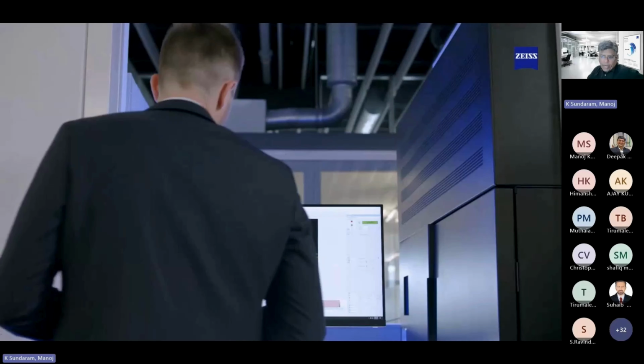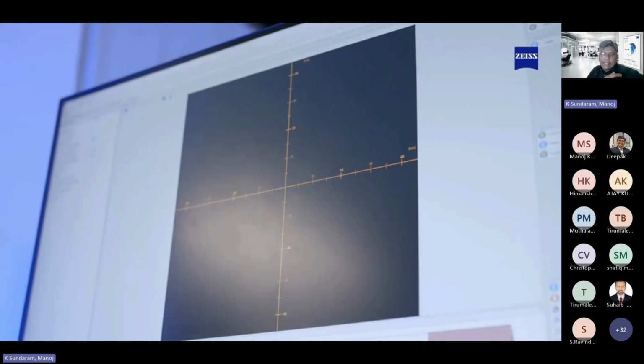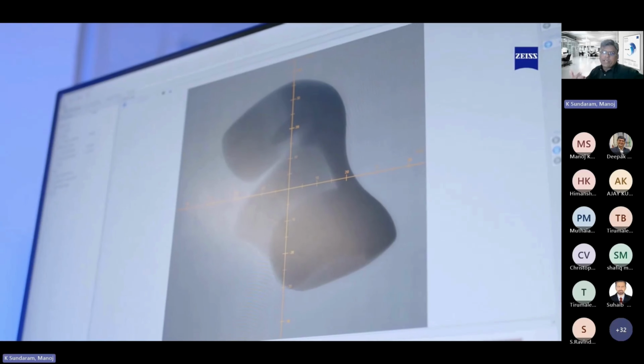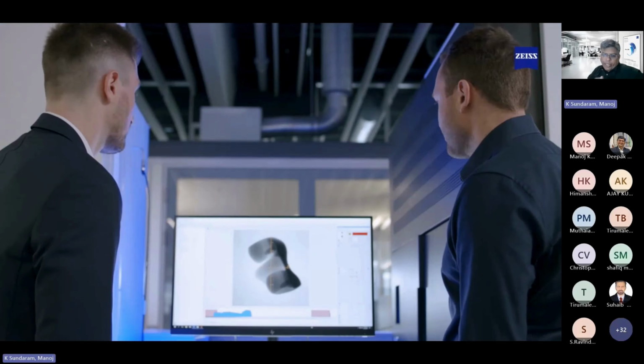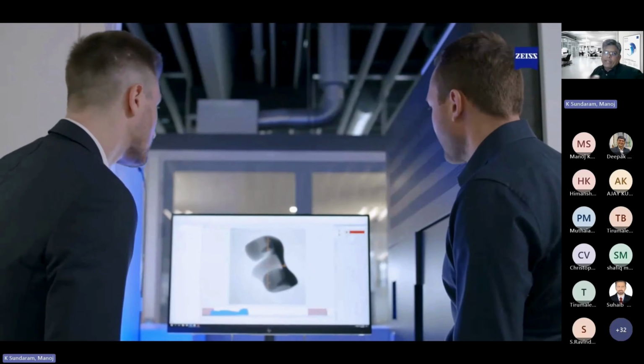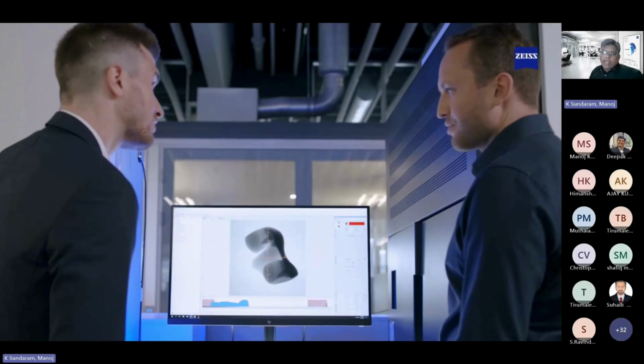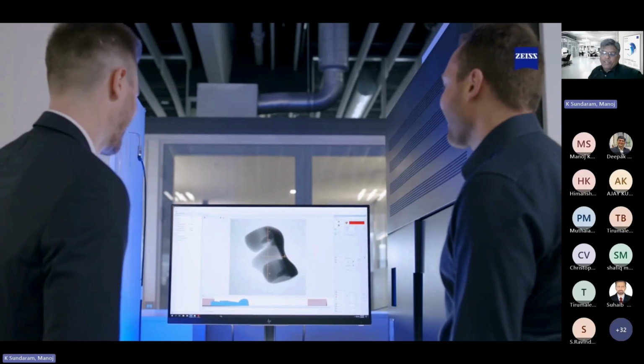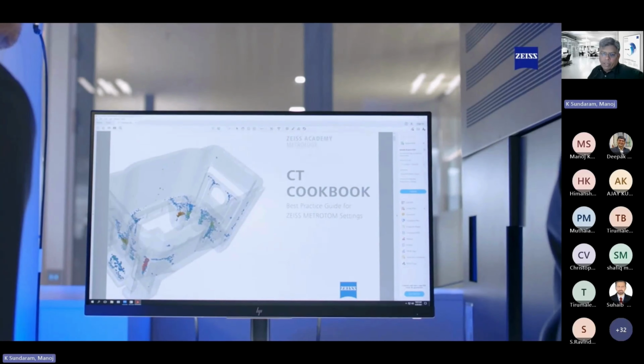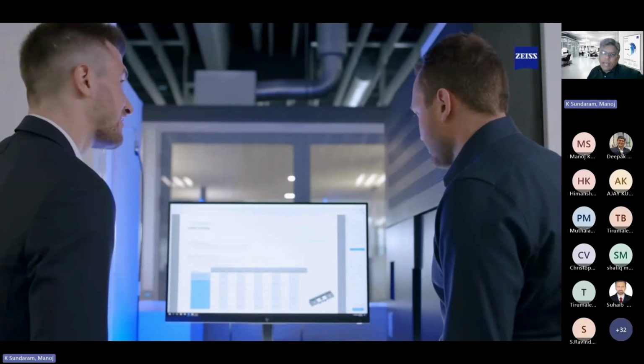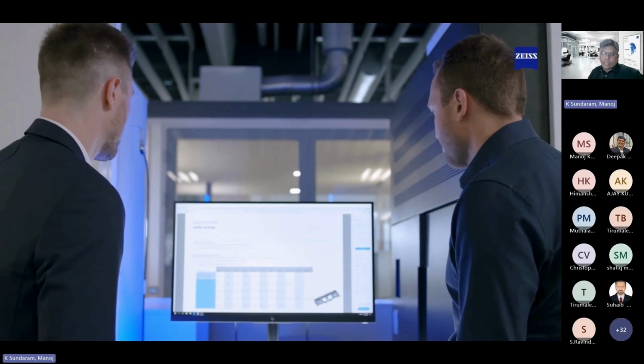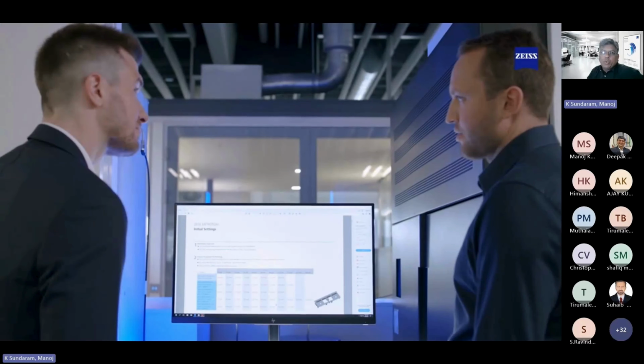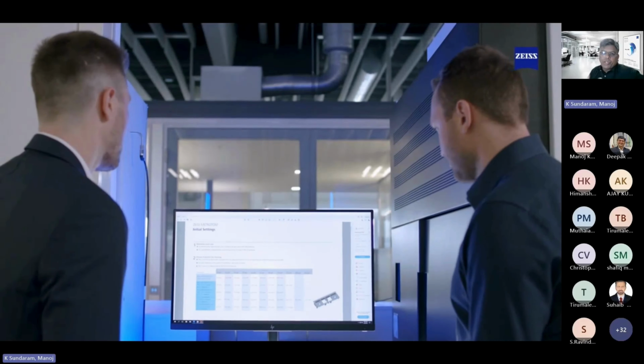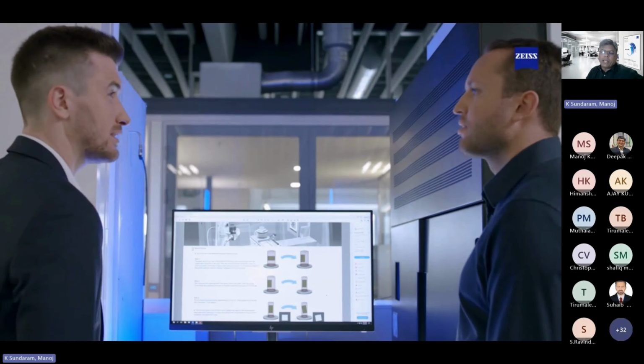Then you have to push the button, then the window closes, and then you have X-rays passing through the part, collecting all the data, about 3,600 orientations of the part. The part gets rotated. Then you collect orientations of the part, then combine all of them. When you take a 2D picture from your camera, you call it a pixel. In this case, this becomes a three-dimensional pixel, which is called a voxel. So you have reverse engineered the part in a span of, say, 30 minutes roughly.